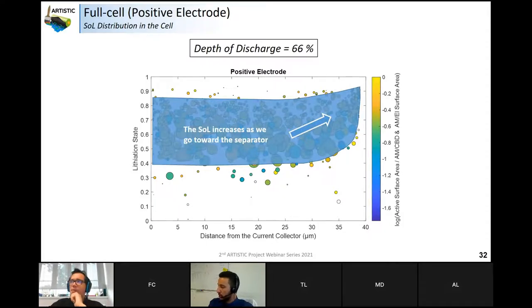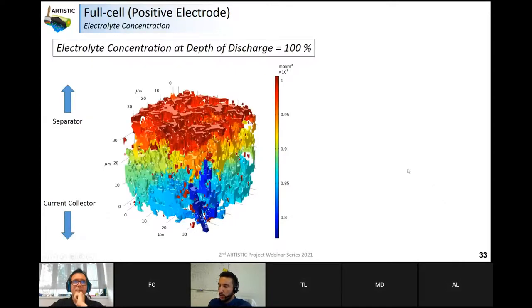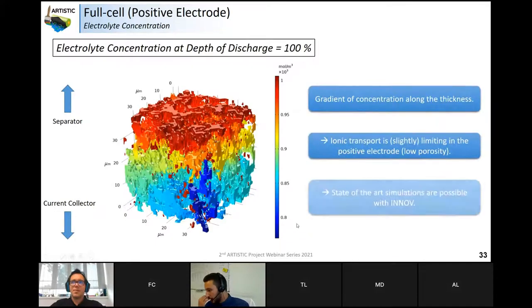an ionic transport limited system. And if we shortly check the positive electrode, so the NMC electrode, indeed you have a strong gradient of electrolytes with much more electrolytes at the top versus the bottom of your electrode, which is quite depleted in lithium ion. So which might explain why you have more lithiation at the top versus at the bottom. So yeah, basically what I was saying, this tool INNOV really allows you to have a strong basis to build state-of-the-art experiments and simulations.